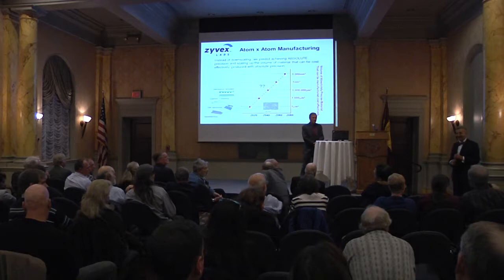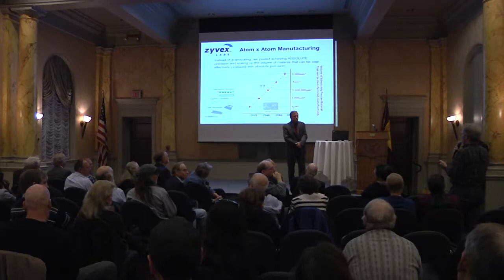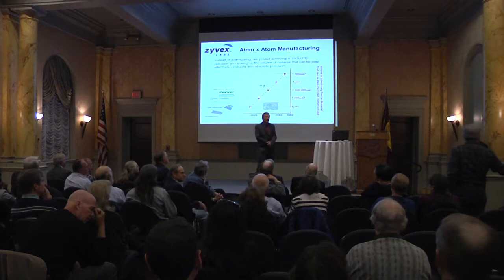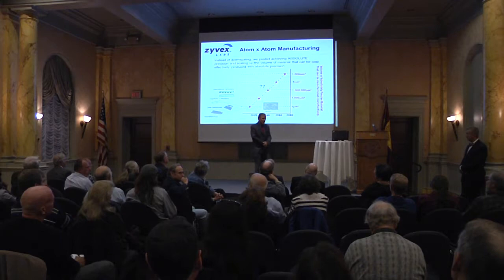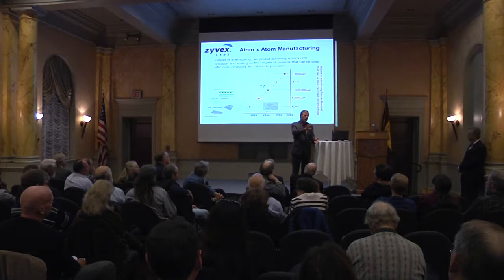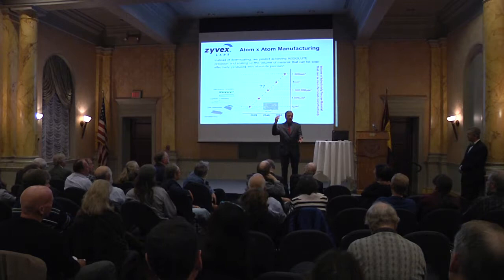Patrick Alsop, I was looking at things like your 3-nanometer squares, and there are other light spots around. If you have something that did not go as planned, can you capture it and have it come out as planned? Yeah, actually right now we can, in the vernacular of mask making in litho, fix opaque defects. We can't fix currently clear defects. If I miss a hydrogen atom, I can come back and image that and remove a hydrogen atom. What currently I can't do, though we have some hints of ways we might be able to do that reasonably well locally, is put hydrogen back down where it's been removed. So if I make a mistake and remove a hydrogen atom I don't want to remove, I don't know of a very good way right now to repair that.